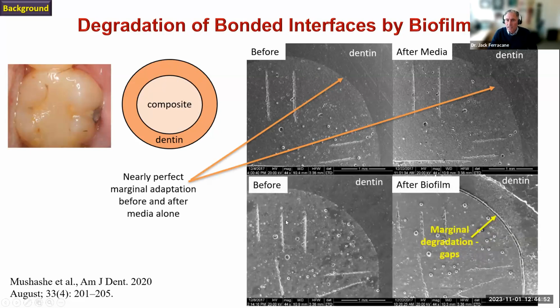In contrast, this is the before and after for the restoration when it was exposed to a biofilm for a period of, I think, 1 to 2 weeks. And you can see a dramatic breakdown of the margin because of the biofilm causing degradation of this interface.